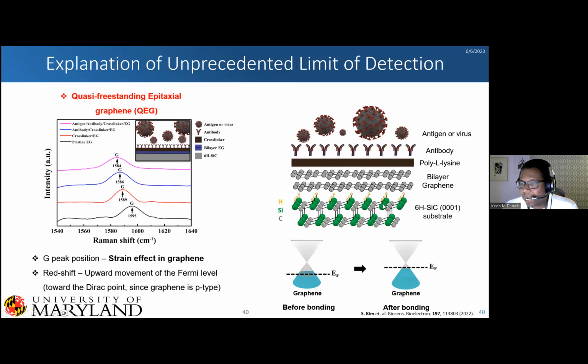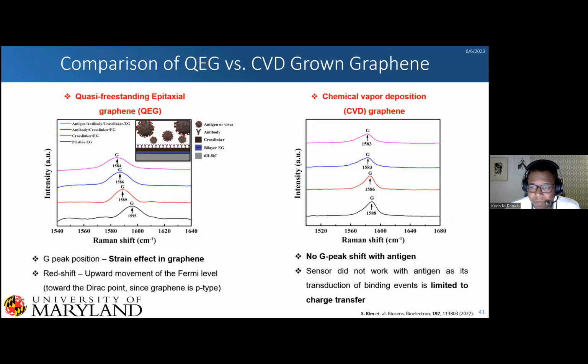This is one reason why our graphene is heavily p-type, because it is dragging all the electrons from our material down. And so when we put down our poly-lysine, it's having an opposing polarization field. And so this is a strain effect being applied to our graphene here. And when we have a binding, then we have this kind of competing strain effect that causes a decent amount of strain in our graphene, resulting in this change in carrier concentration.